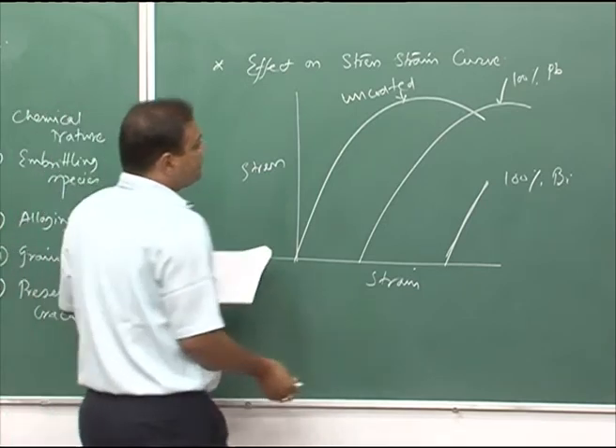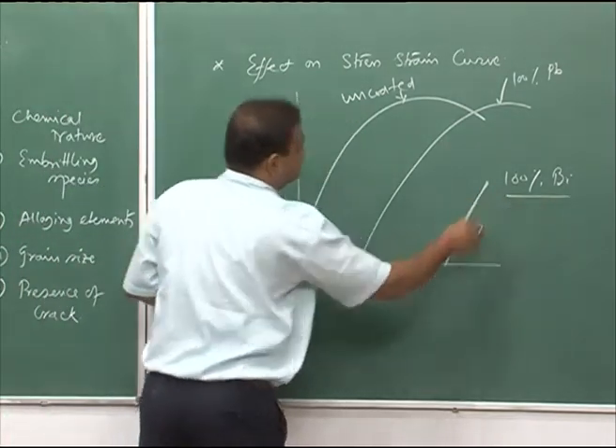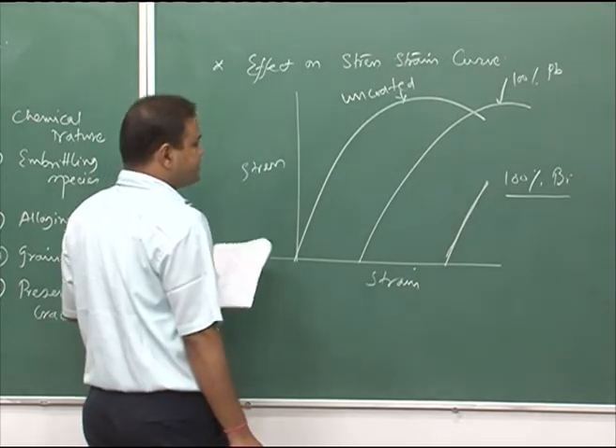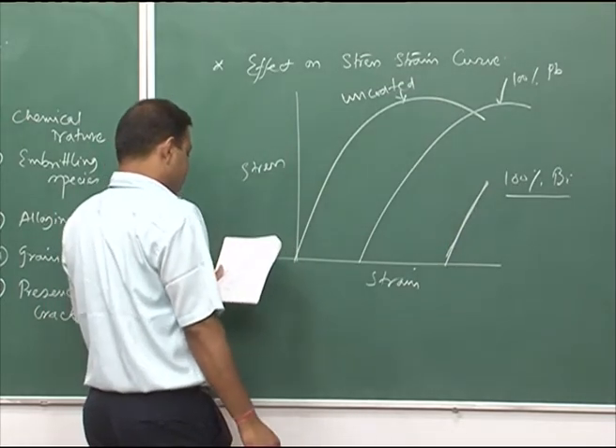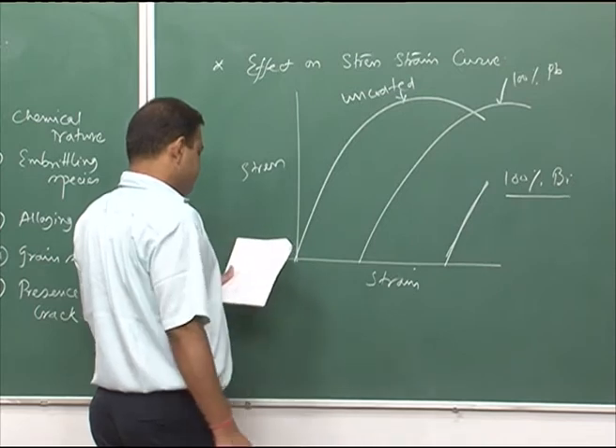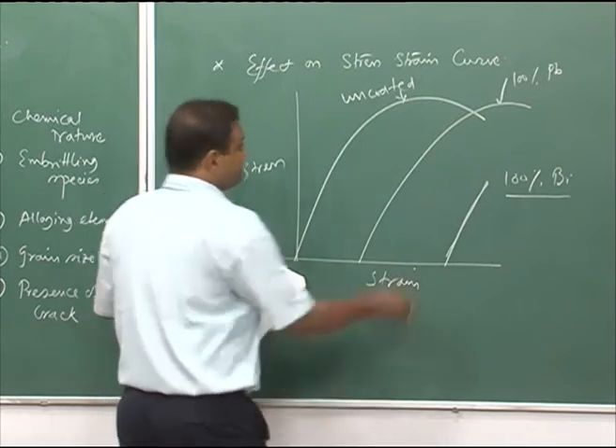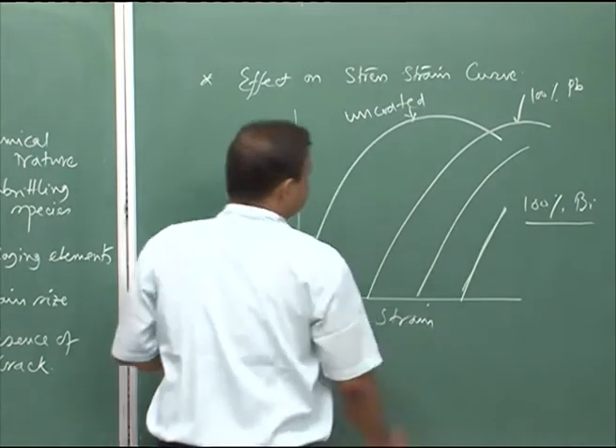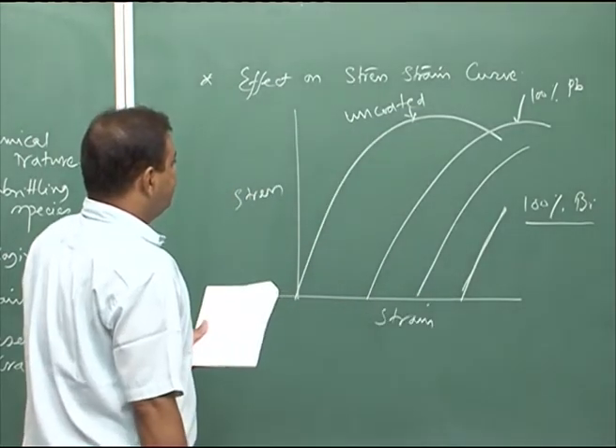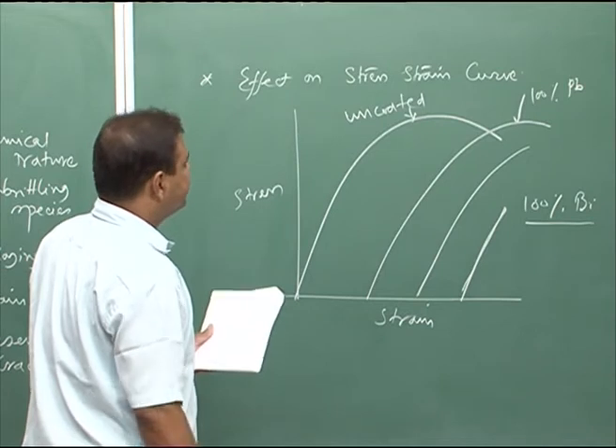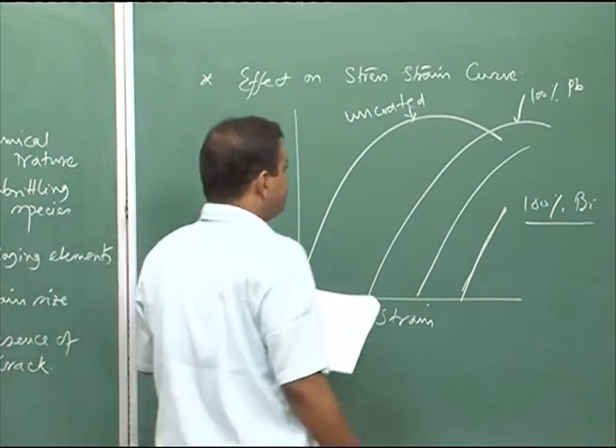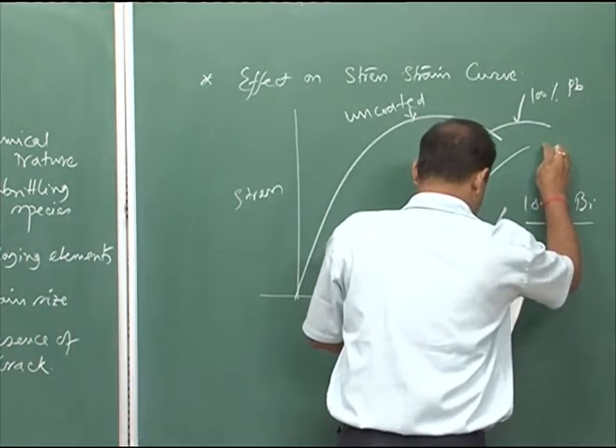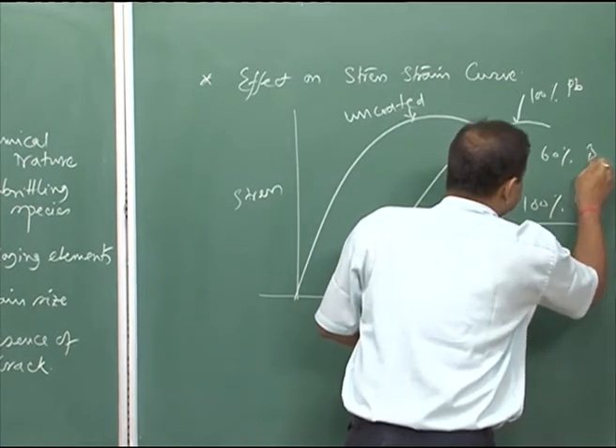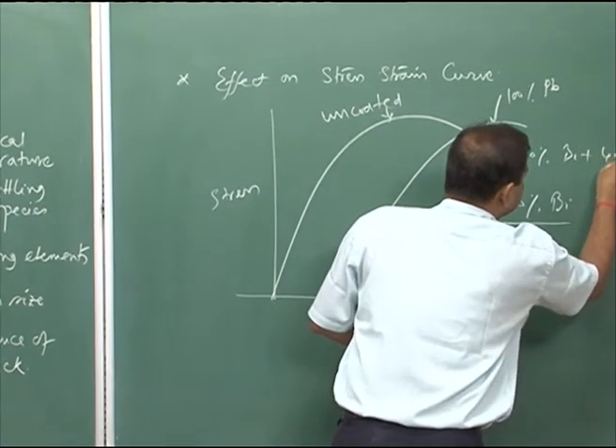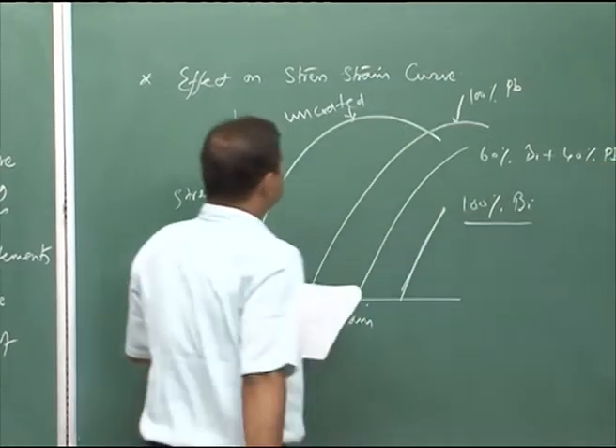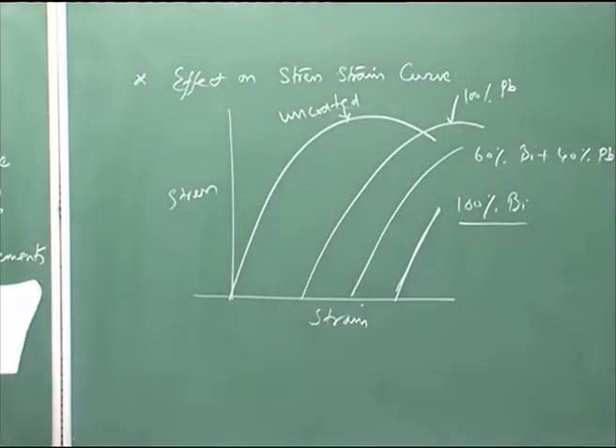and if you alloy this 100% bismuth with lead, let us say 20%, let us say 40% lead, then you can have little improvement, and there will be delayed embrittlement. So, this is let us say 60% bismuth plus 40% lead. So, this is basically the effect on stress strain curve.